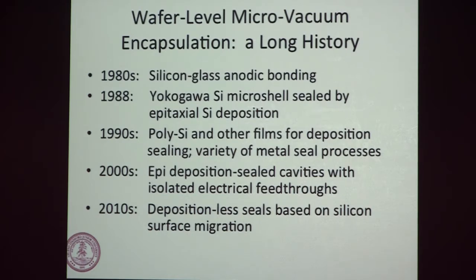It was sealing up microcavities, so the devices were in a vacuum shell, each device on the wafer in a vacuum shell. There was an NSF visit to Japan, and they saw this work, and it had a huge impact on the US in terms of modifying research priorities, even some of mine. I was a participant in these various other sealing processes through the 90s. In the 2000s, there was work at Stanford in Tom Kenny's group on using epitaxial silicon depositions. The big contribution was getting electrical interconnects through the vacuum. And finally, recently, we're working on doing the sealing in epitaxial layers or single crystal silicon layers with no deposition at all, which is kind of interesting.